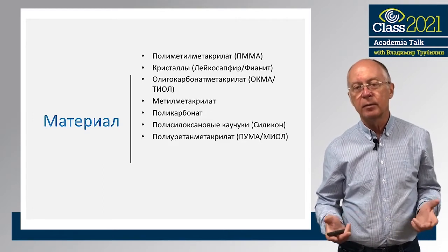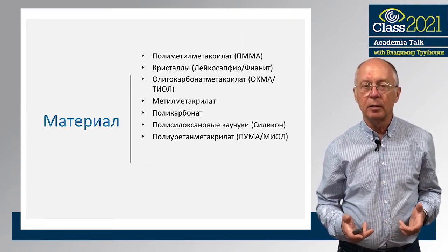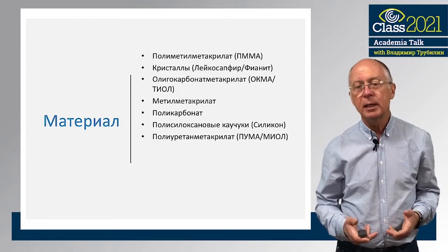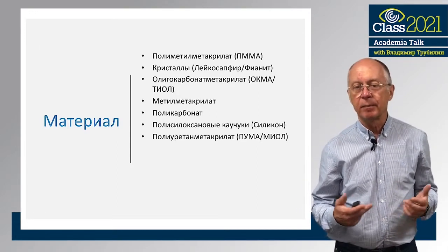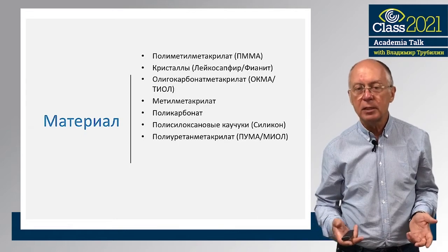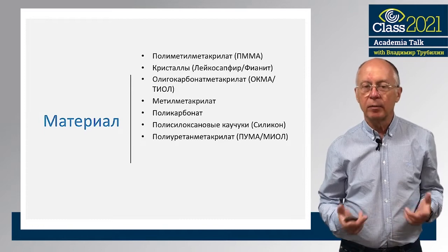Lenses made of this material were manufactured in Russia for some time. However, unfortunately, it turned out to be unstable as the polymerization of the material continued in the eye, which led to the lens clouding, and in most cases these lenses had to be removed and replaced with other models.